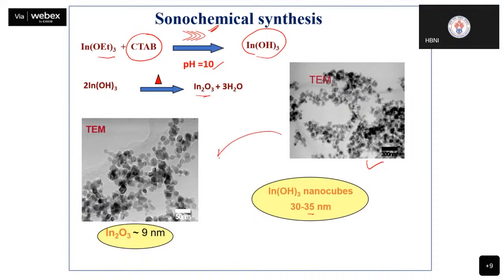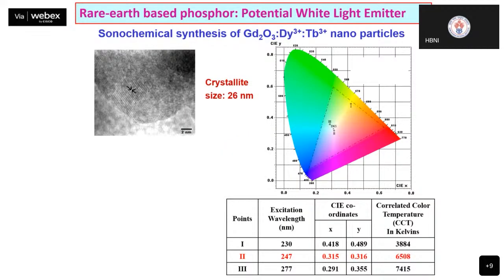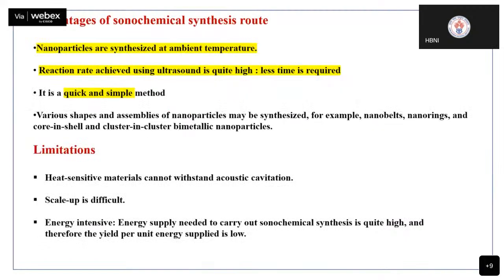And when we further decomposed it, we got indium oxide, which is still smaller in size, of the order of 9 nanometer. Okay, again, an example of sonochemical synthesis. Advantages: you're getting your synthesis done at ambient temperature.